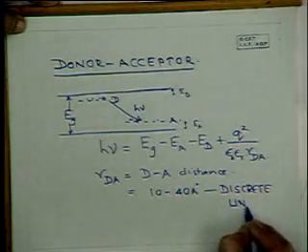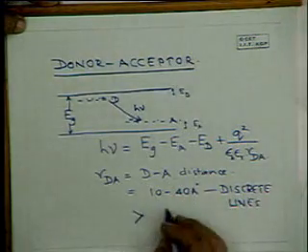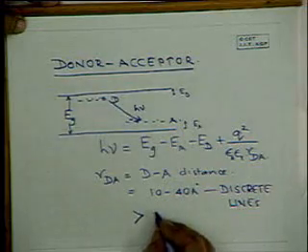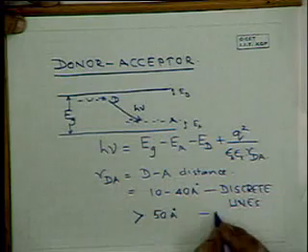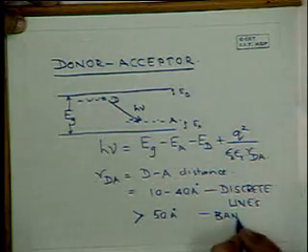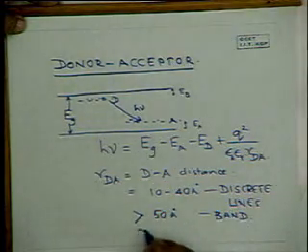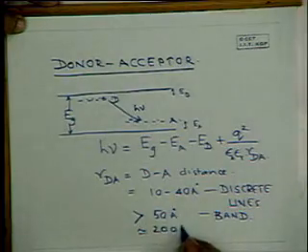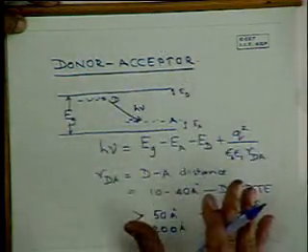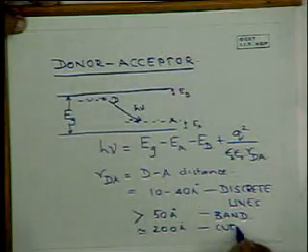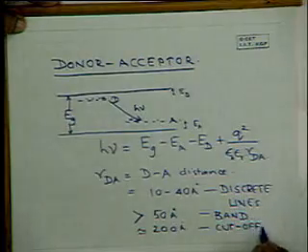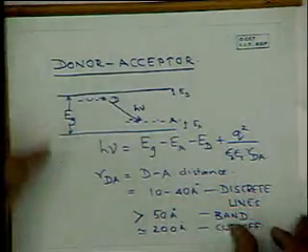in the spectrum. But if this is more than, say, 50 angstroms, then the number of lines merge and then you get a broad band. And at about 200 angstroms, because the distance between donors and acceptors becomes large, the probability becomes small, and then you get a cutoff. What is the nature of the spectrum?